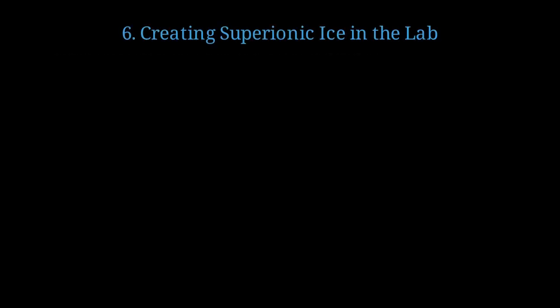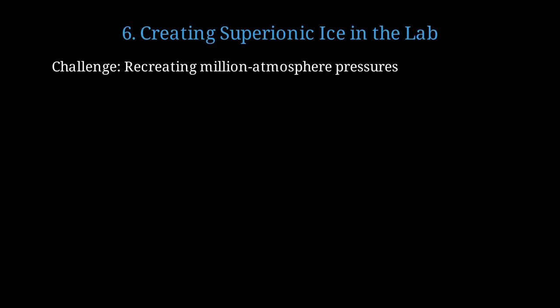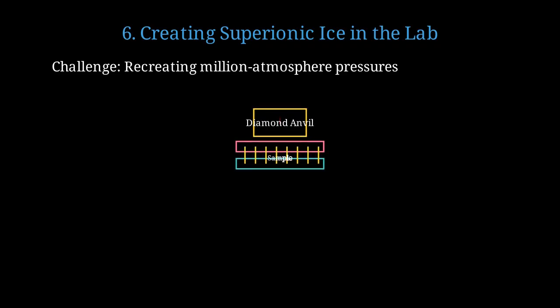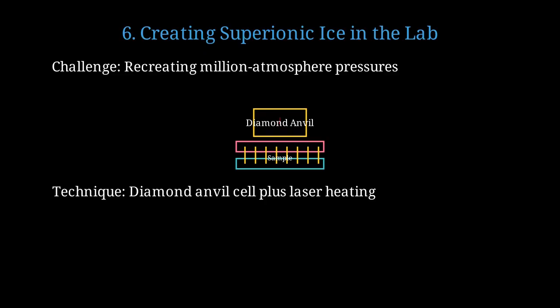Recently, scientists have successfully created Superionic ice in laboratory experiments. The main challenge is recreating the million atmosphere pressures and extreme temperatures found inside ice giants. Scientists use diamond anvil cells, where 2 diamonds squeeze a tiny water sample between them, creating the necessary extreme pressures. They combine diamond anvil cells with powerful laser heating to simultaneously achieve the high pressure and high temperature needed. The experiments reach about 2 million atmospheres and 5,000 Kelvin, matching conditions inside ice giants. Using X-ray diffraction, researchers confirmed the unique structure of Superionic ice with frozen oxygen and mobile hydrogen.